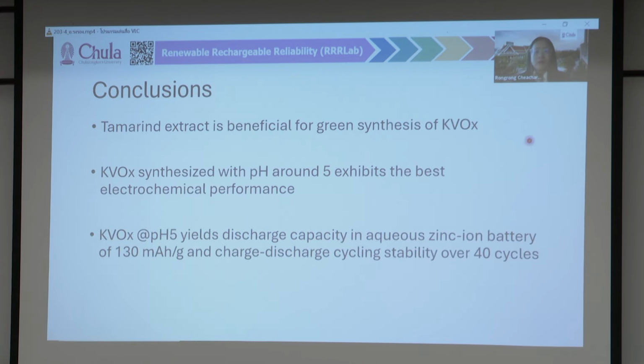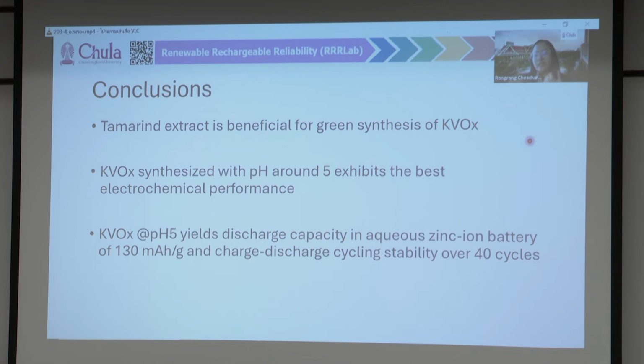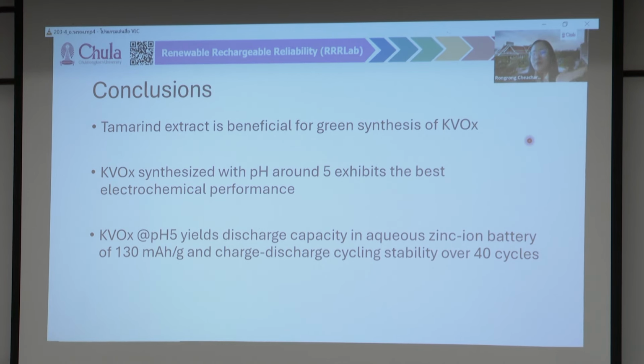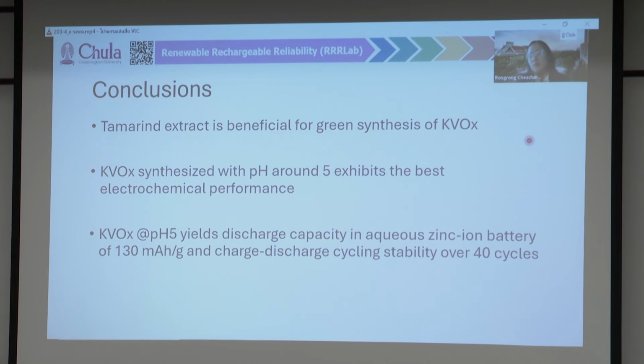So in conclusion, this work really shows that the tamarind shell extract is beneficial for a green synthesis of KVOx, and it's possible to synthesize this way at a much lower temperature and much shorter time. So it's more energy saving so that we can produce more and more materials. The second point is that the potassium vanadate synthesized at a pH of around 5 seems to be the best cathode material, as it has quite high activities in the cyclic voltammetry graph, as well as yielding the highest discharge capacity of 130 milliamp hour per gram, and the cycling stability over 40 cycles.